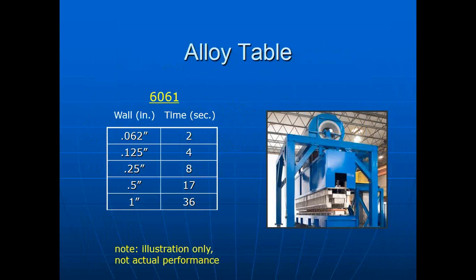Alloy table might look like this. This is an illustration only. It's not intended to portray the actual performance of any particular quench. But in this case, this quench, if I run a 62 thousandths wall, I will cross the entire critical temperature range in 2 seconds. On a 125 wall, it takes 4 seconds. On a 250 wall, I'm up to 8. On a ½ inch, 17 seconds. 1 inch, 36 seconds.